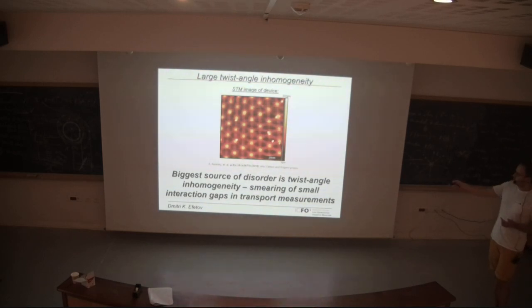But this is, for example, an STM image of a recent paper which just came out, I think, a week ago in Nature by the Columbia STM group. This STM image gives you the device, and you can basically see the evolution of the moire periodic potential as a function of spacing. This is basically 20 nanometers here, so this whole graph is 100 by 100 nanometers. And maybe you can see that here the lattice constant is bigger than here, right? So something adiabatically changes in the device.